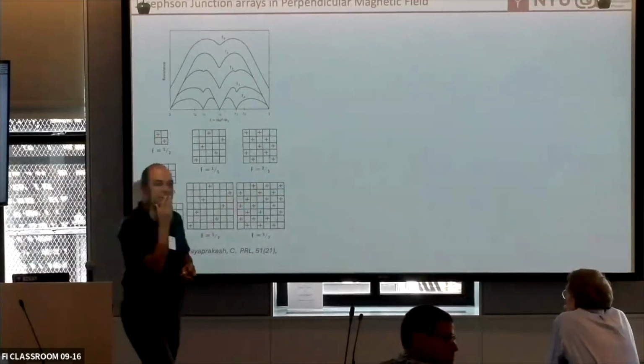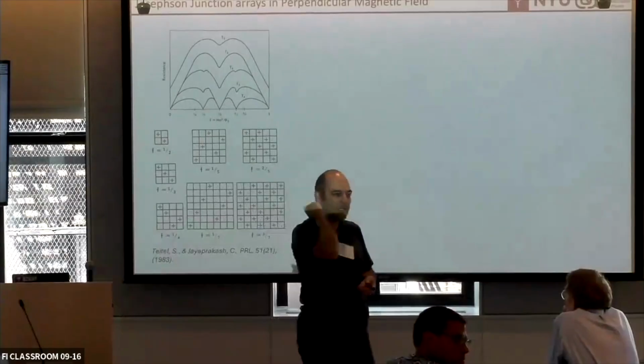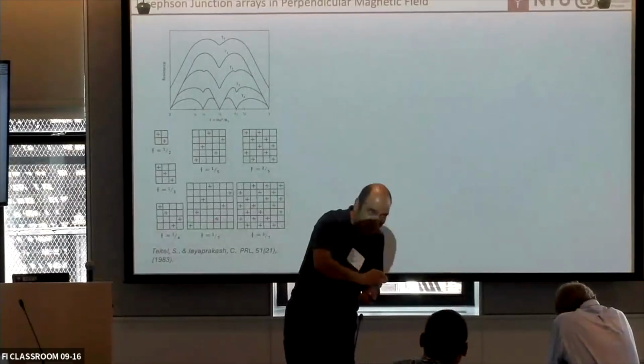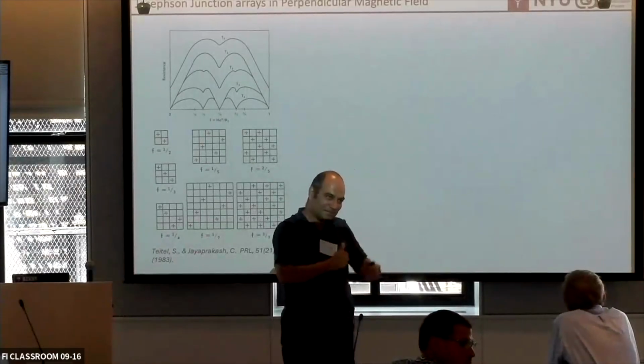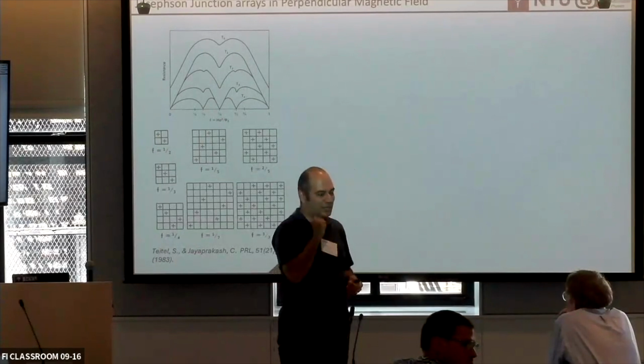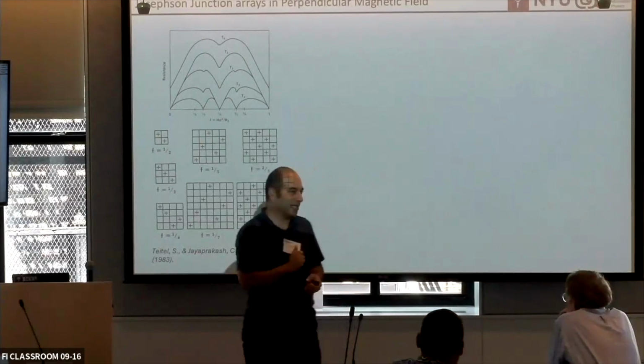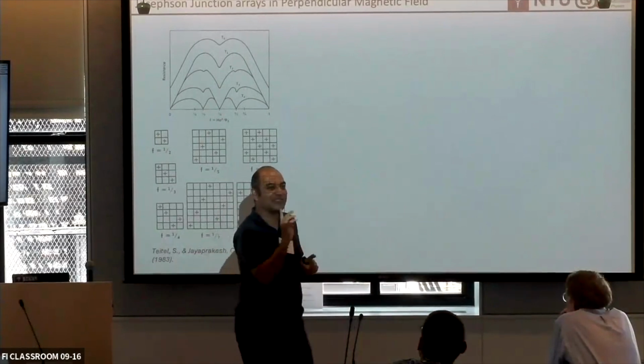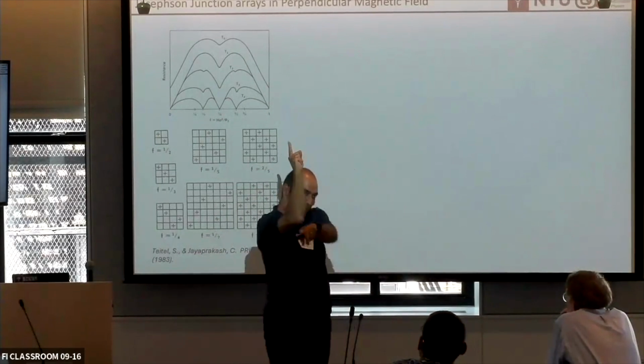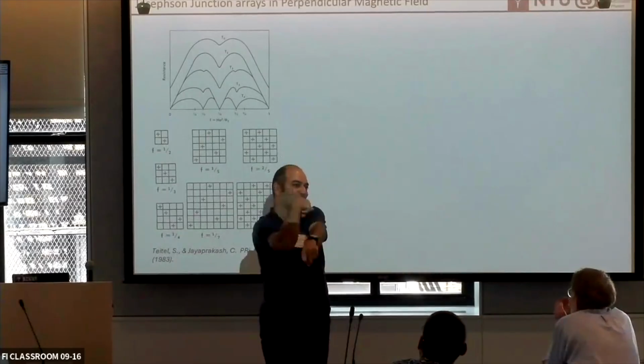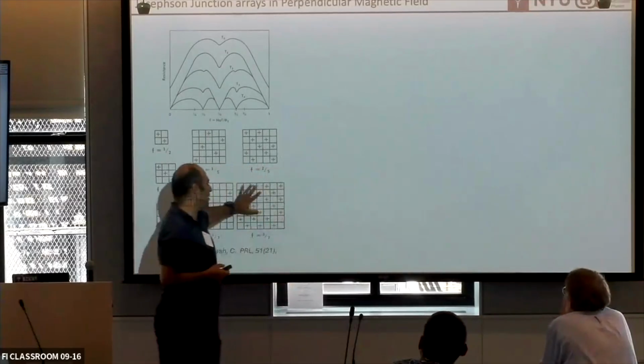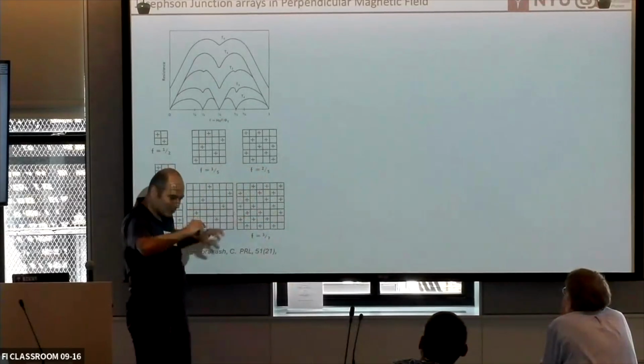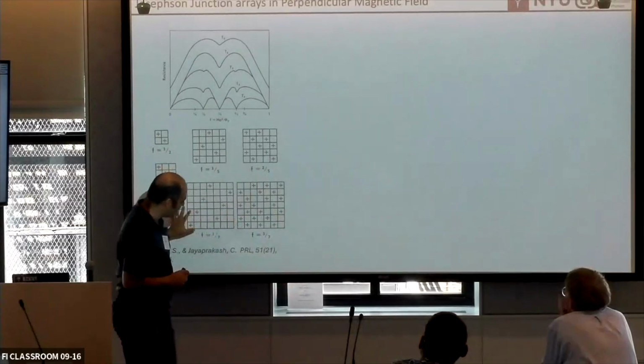Yes. So this is like actual magnetic flux. This is actual magnetic flux. So I just turn on the magnetic field. So there is spin orbit coupling plus magnetic flux that you control. Exactly. And for the filling factor, the only thing that matters is out of plane, but I can also put in plane. And I'm going to do it. Right? In all these experiments, they just put something out of plane. Right? So just tune it and then something appears.